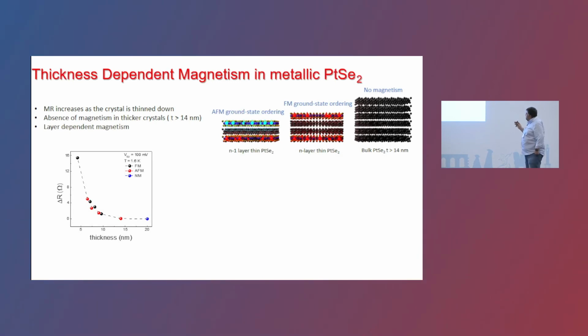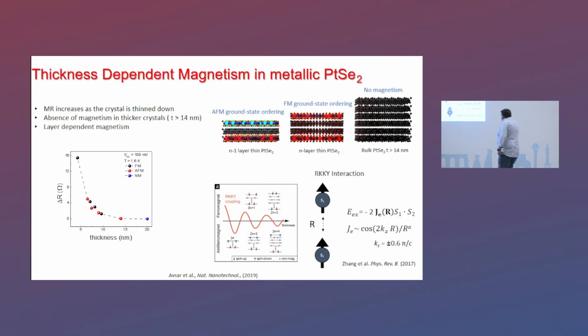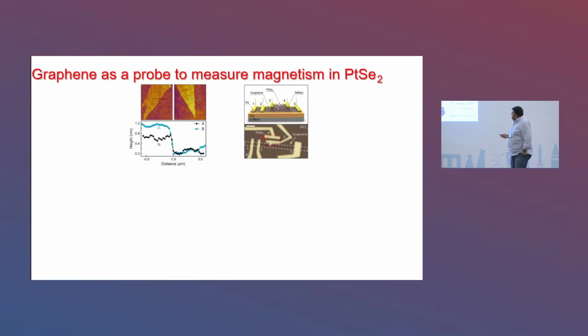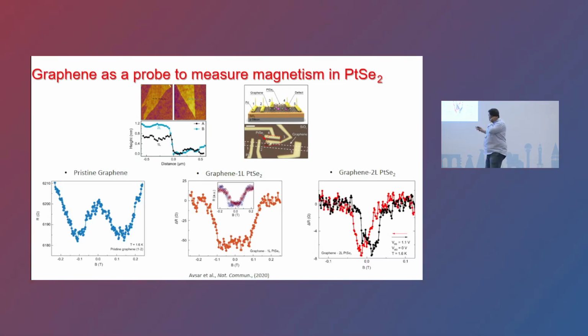We had more detailed studies, but basically what we see is that in the material you have a ferromagnetic or antiferromagnetic ground state ordering, and then by just adding or removing one layer, the material turns into a ferromagnet. And whenever you go above 14 nanometers, the material becomes non-magnetic. We explained this with the RKKY interaction, and basically these magnetic moments formed due to the platinum vacancies are giving the magnetism, and all these thickness-dependent measurements are in good agreement. Then we also studied whether the monolayers and bilayers of this defective material are magnetic, and we similarly see layer-dependent magnetism down to the monolayer in this material.